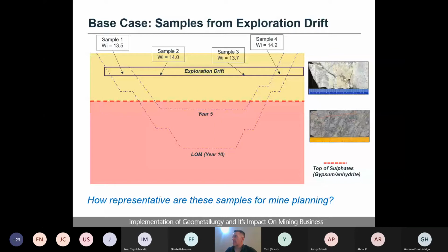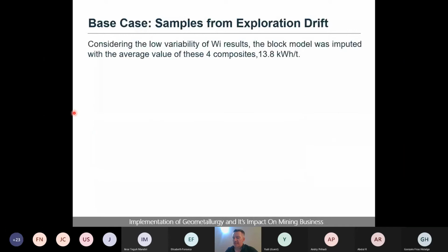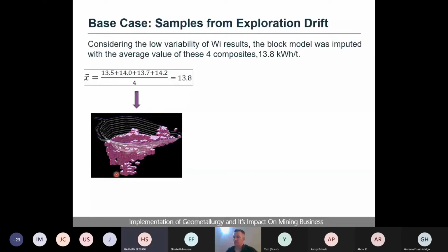So, our base case: samples from exploration drift. As the laboratory test results display low variability, this is the result. The block model was imputed with a single work index, that is to say, 13.8 kilowatt hours per ton. So here we have the block model imputed with the value. As we can see, the plan used a single work index parameter.